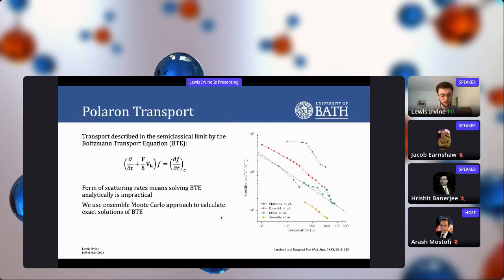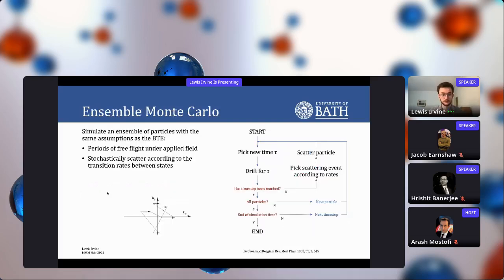So we solved the Boltzmann transport equation, which is written here. Our new forms of the scattering rates are a little bit complicated, so solving the BTE analytically is impractical. So what we do is we use the Ensemble Monte Carlo approach to solve the Boltzmann transport equation stochastically and to calculate essentially exact solutions to the BTE. I won't go into too much detail, but you essentially follow the assumptions of the Boltzmann transport equation. You have these periods of free flight under an applied field, and then you stochastically scatter your particles between states according to the rates that we described earlier. This has applications beyond what we're doing, which is the steady state bulk. We hope eventually to do device scale simulations and also look at transient effects as well. But this is just the bulk for now.